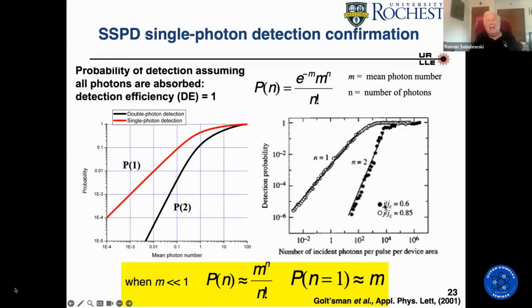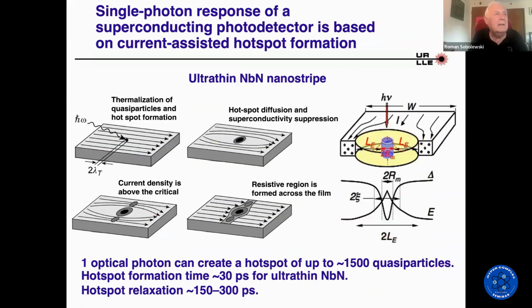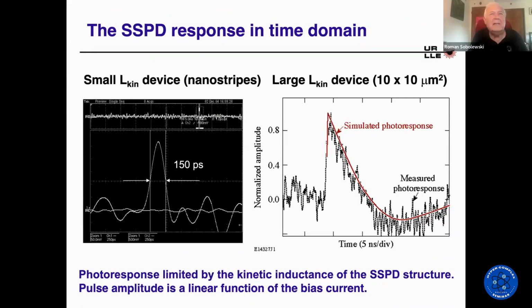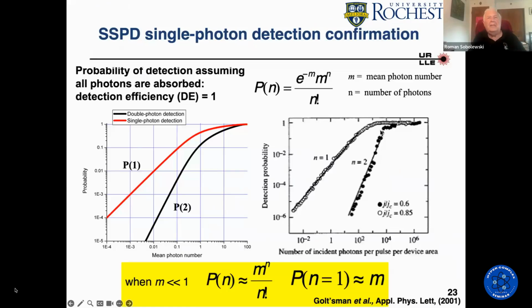Of course, I changed the bias current so I could be either very close to that critical current or farther away. This way I could control my threshold. And you can see by controlling the threshold, I could have a detector which detects single photons, and under this condition, the same detector would detect only photon pairs. Because, as you imagine, the higher the photon number, the higher the probability of having a detection event.